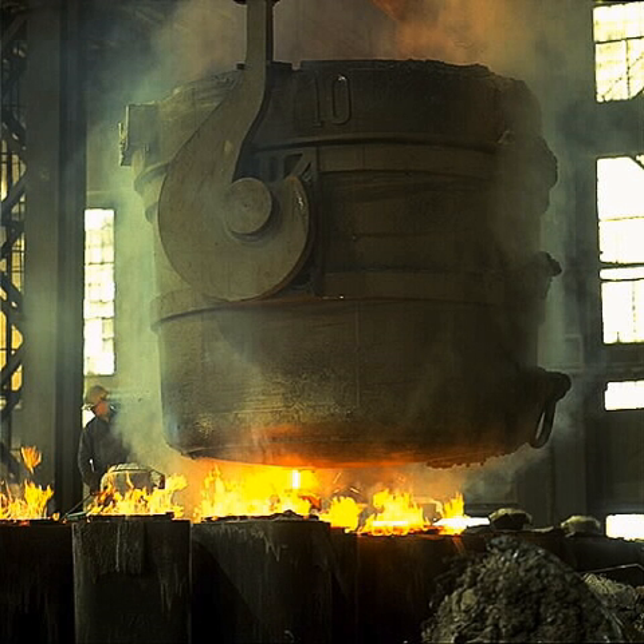Cast iron's properties are changed by adding various alloying elements or alloyants. Next to carbon, silicon is the most important alloyant because it forces carbon out of solution. A low percentage of silicon allows carbon to remain in solution, forming iron carbide and the production of white cast iron. A high percentage of silicon forces carbon out of solution, forming graphite and the production of gray cast iron.